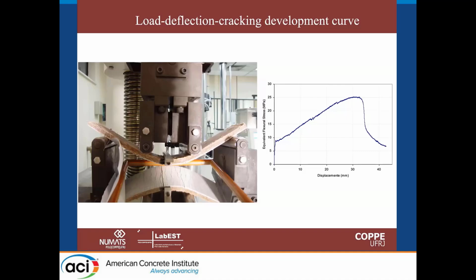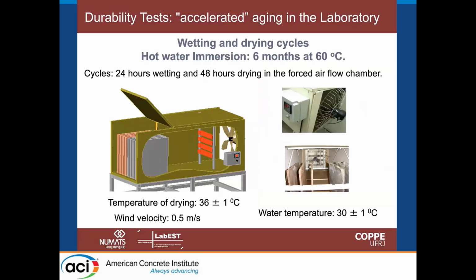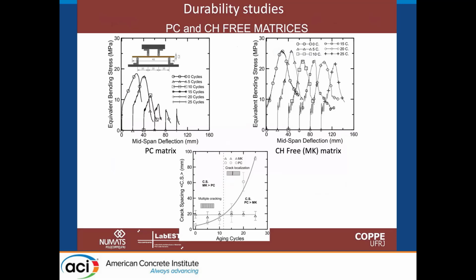But when we have short fibers, we can also have nice behavior, not at this level of deflection, but we can have 10, 15 millimeters deflection with 7, 8 MPa or even 10 MPa under bending with short fibers as well. A big concern is the durability of these materials. We did some cycles of wetting and drying to see how this material behaves under changing humidity and temperature. And we see here the necessity to use CH-free matrices.